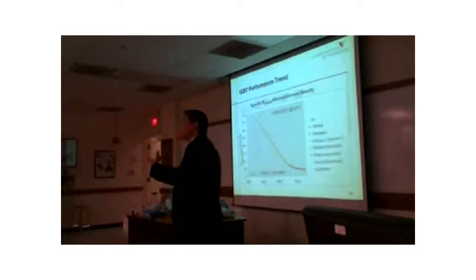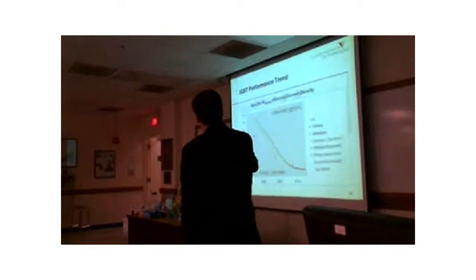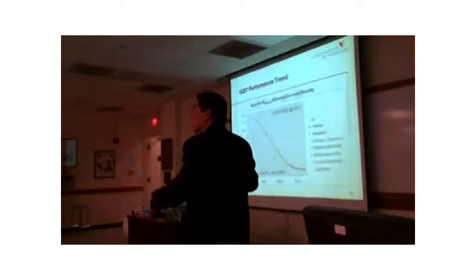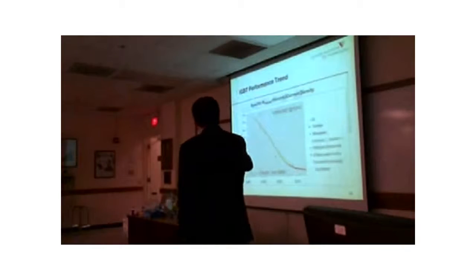It's hard to compare the IGBT performance among different vendors because they all try to show you the best number under the specific testing condition. So over the years, I was able to collect all those data and normalize them into this so-called specific RDS-on. This way you're not comparing a small die with a very large die. That's not an apple-to-apple comparison. We also specify the IGBT has to be measured at 125 degrees C. They have to have the same switching performance because different manufacturers have a slow IGBT, which has great conduction capability, but is not so good at fast switching. So over the years, you can see it came all the way down from 80 milliohm centimeter squared to maybe a single digit now.